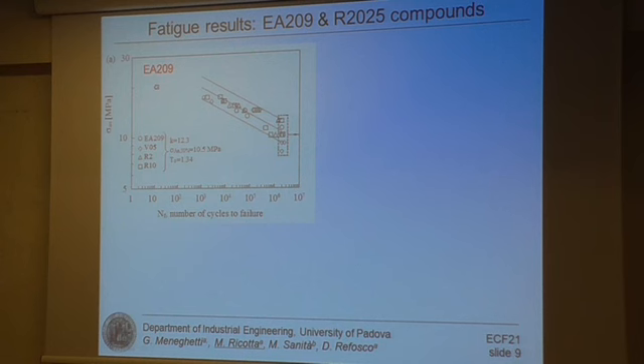Now I'm moving from fatigue test to fatigue test results. Here we can see the fatigue test results obtained in the case of the compound made by virgin polypropylene. All the fatigue data can be summarized in a single scatter band in terms of stress amplitude referred to the net section, despite the different notch severity. Therefore, we can conclude that the material is notch insensitive, with a reference fatigue strength evaluated at 2 million cycles and 50% survival probability equal to 10.5 megapascal, and an inverse slope of the fatigue curve equal to 12.